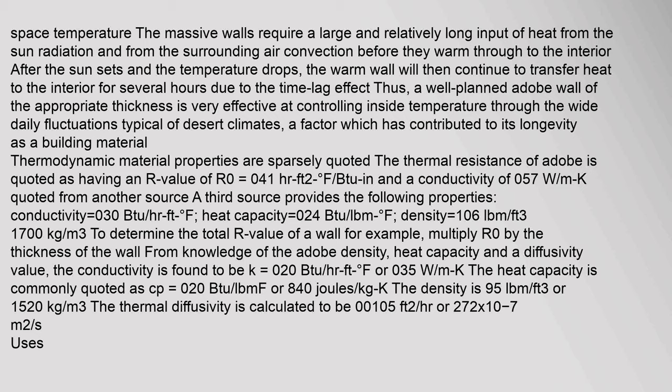Thermodynamic material properties are sparsely quoted. The thermal resistance of adobe is quoted as having an R-value of R=0.041 hour·feet²·degree F/BTU·in, and a conductivity of 0.57 W/MK from another source. A third source provides the following properties: conductivity equals 0.30 BTU per hour·feet·degree F, heat capacity equals 0.24 BTU/LBM·degree F, and density equals 106 LBM per foot³.